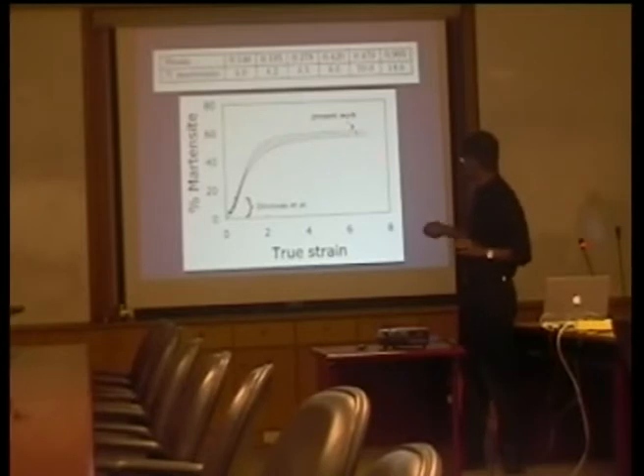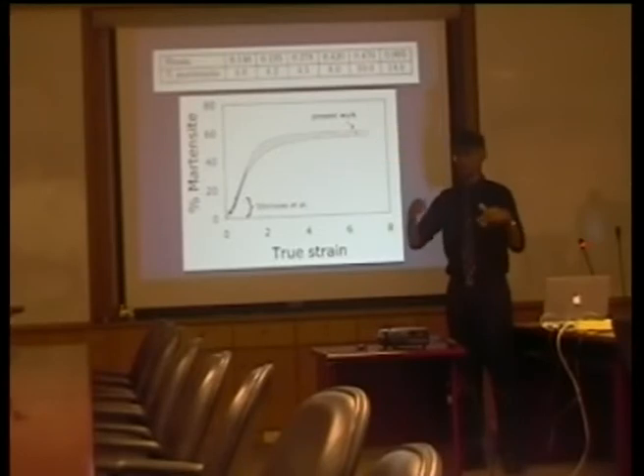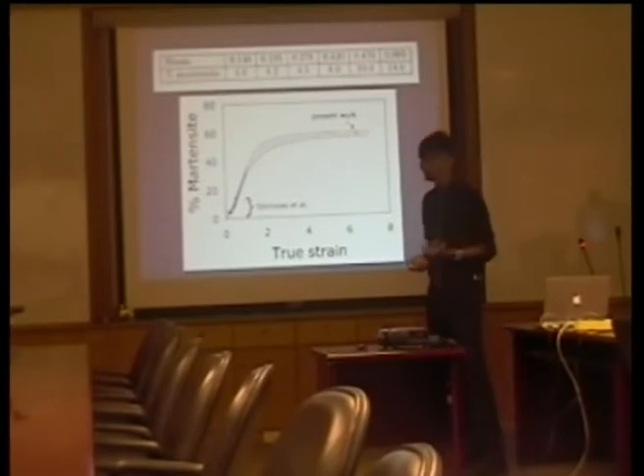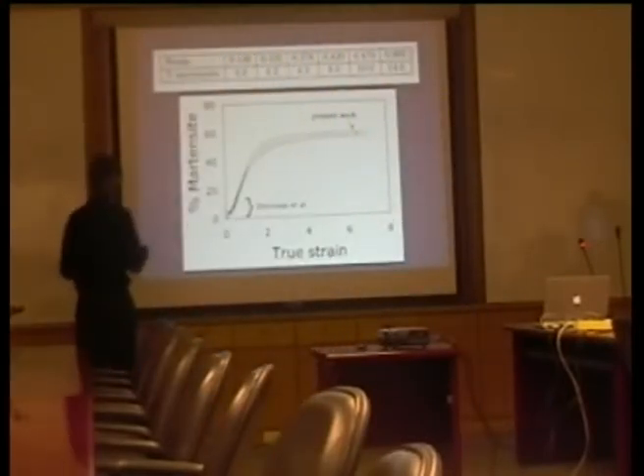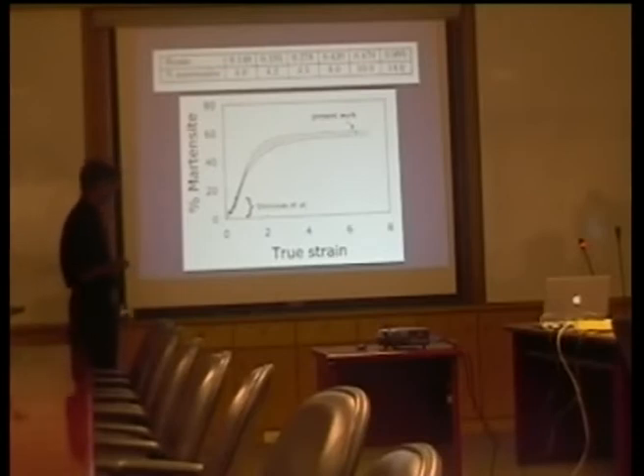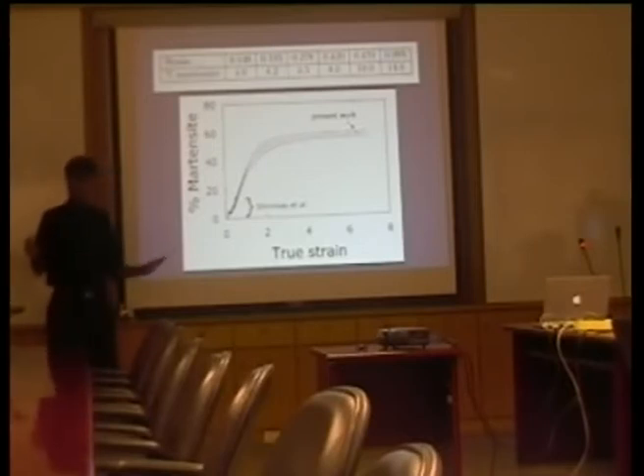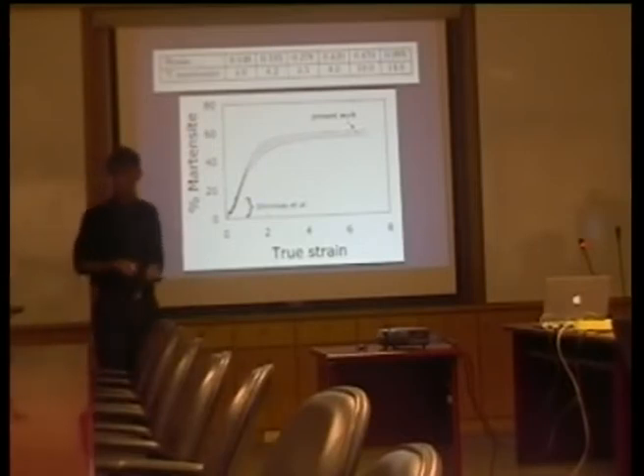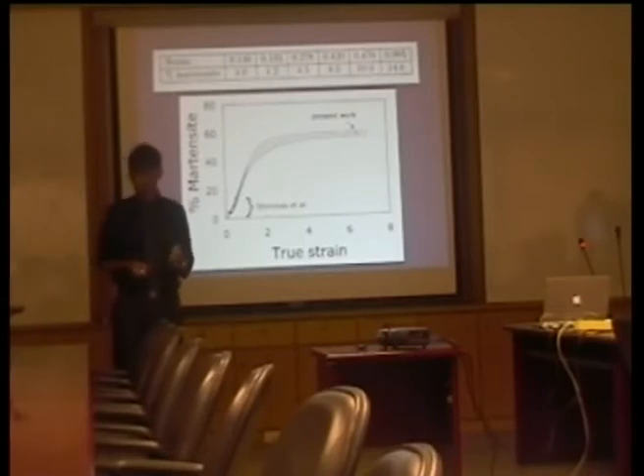So we have not biased this curve in any way. We have not suggested that the curve should be of that shape, but the neural network identifies that it should be of that shape. And the reason why it's exciting is that it predicts that if the strain is less than 2, then we don't have mechanical stabilization. If the strain is greater than 2, then it doesn't matter how much I strain it, I will not get transformation. So our prediction is that this is where mechanical stabilization begins.